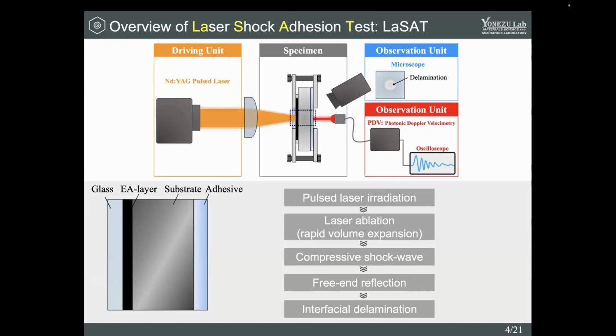This is a close-up view of the specimen parts. As a specimen, there is a ring-shaped adhesive on the substrate surface. And the EA layer is responsible for generating plasma pressure through ablation. This study used a silicon oil-based viscous fluid. In order to keep the thickness of the EA layer constant, sapphire glass is arranged.